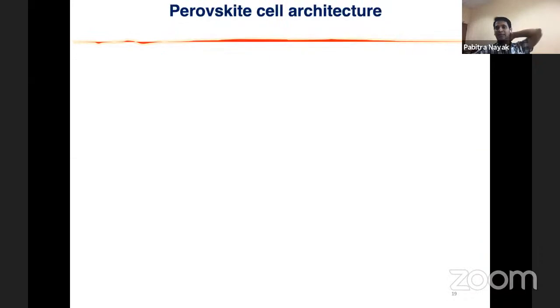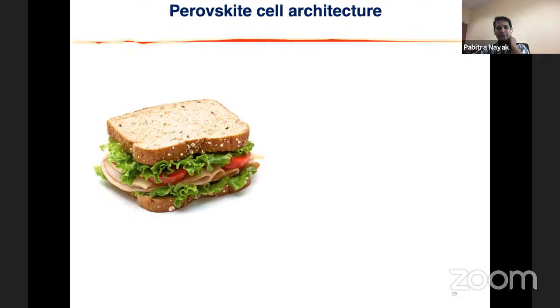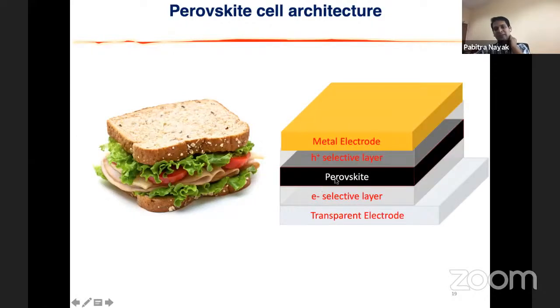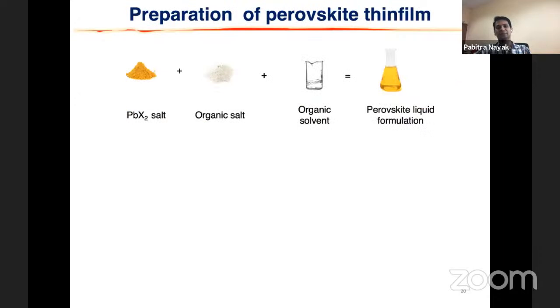Now, what does a perovskite solar cell look like? Well, it is a sandwich. Pretty much. I'm serious. It's like a sandwich, but not the sandwich that you can eat, but a sandwich of electronic materials. So the perovskite is sandwiched between two different types of materials and electrodes. Now, how do we prepare those things? It's damn simple. You take a lead salt and you take an organic salt. They're very cheap chemicals. Then you take them in a beaker, add some organic solvent that can dissolve these two. And your perovskite formulation is ready.